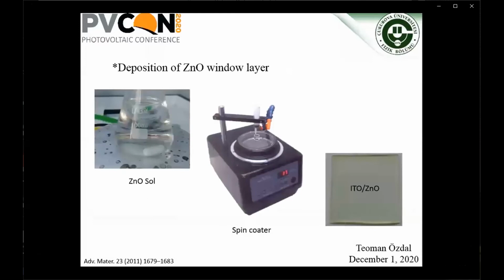Our talented collaborator Merhan, aka Magic Hand, optimized the deposition of zinc oxide thin film. We thank her. She first increased the amount of stabilizer monoethanolamine in the solution. She also heated the solution before the spin coating, and then voila. Her optimization of chemical ratios in the solution and thermal treatments before and after the deposition made this work possible.